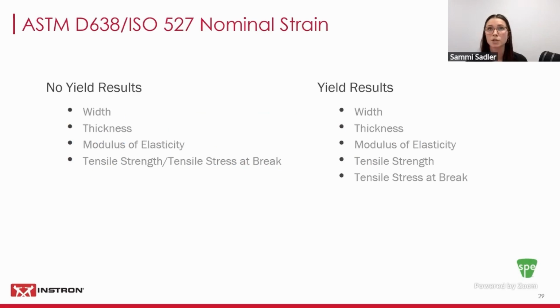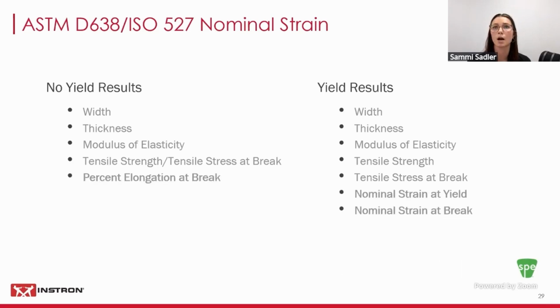So how does this affect your results? When a material does not yield, the results table will include the displayed results up here. So we have our no yield results with our yield results. When compared directly to a material that does yield, it will include similar results, but it will require our nominal strain calculations, our nominal strain at yield specifically, and nominal strain at break. It's extremely important to display the correct results of your material so you're compliant with the testing standards.